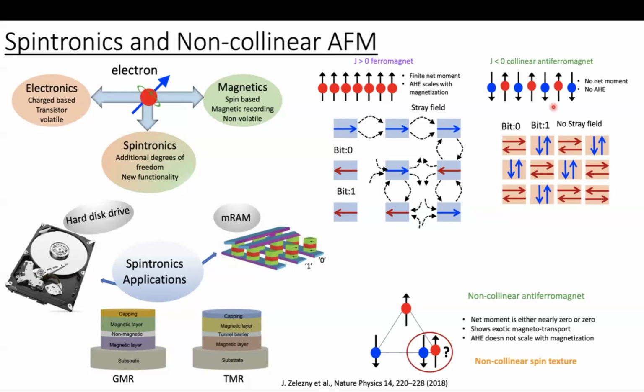Also, there is another class of material called non-collinear antiferromagnet. Suppose you have two spins, let's say red and blue, they are antiparallel, and you bring another spin. Then there will be frustration in this system, and this third spin can be up or down. And then the resulting spin texture will form a triangular lattice. In this kind of system, the net moment will be nearly 0 or 0, depending upon the situation. So in terms of magnetization, it behaves as a collinear antiferromagnet.